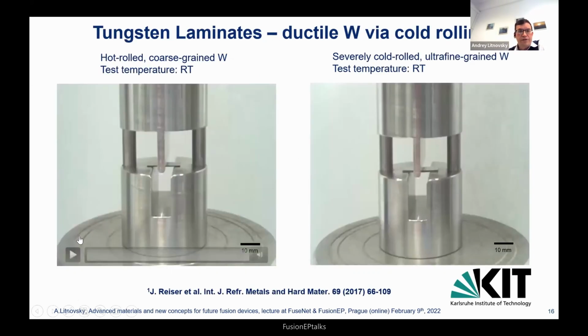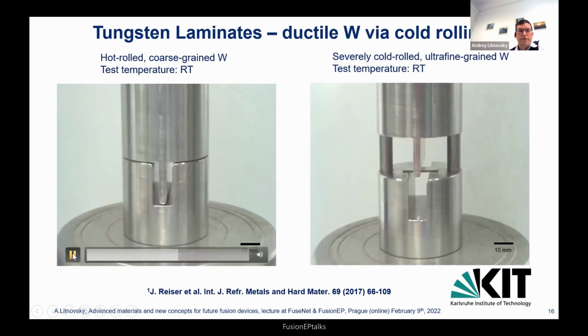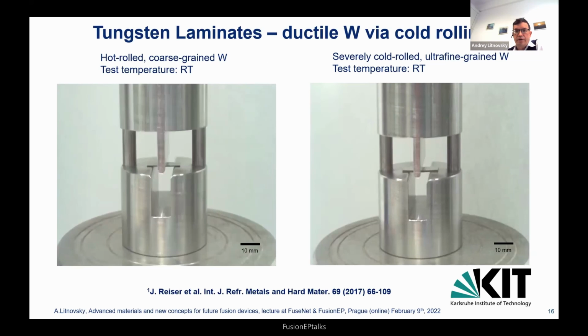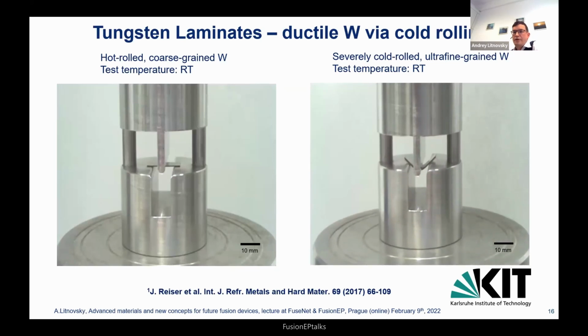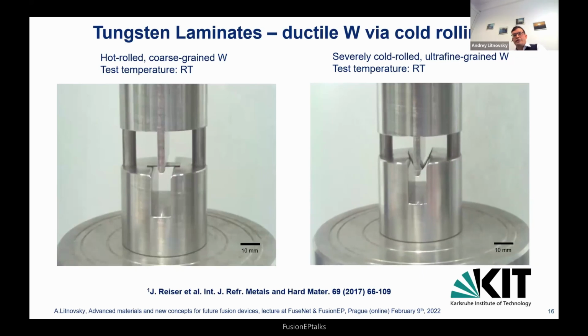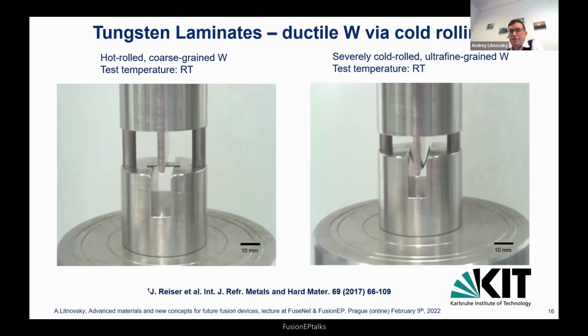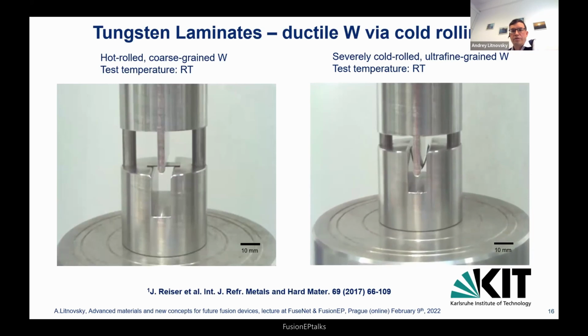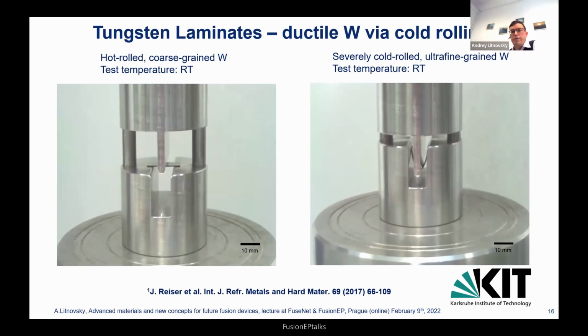How this all works is shown in this small video. On the left side, which I will start right now, is the pure tungsten at room temperature. It breaks simply because it's absolutely brittle. If you put in the tungsten laminate, which is on the right, you can see how it really bends. And it bends, in fact, without even getting destroyed. It was actually quite a viral video from the Karlsruhe colleagues who shared this material with us. So these laminates obviously work.